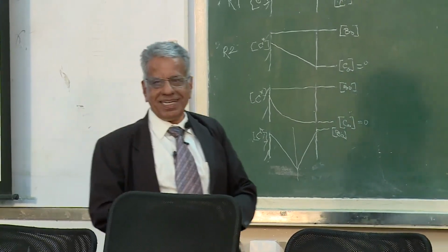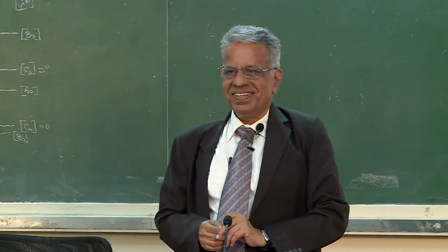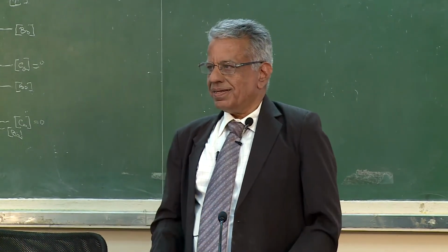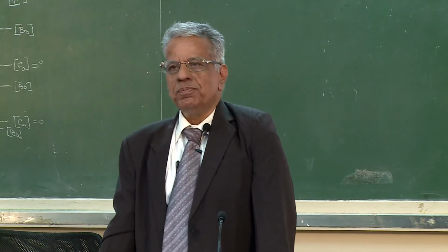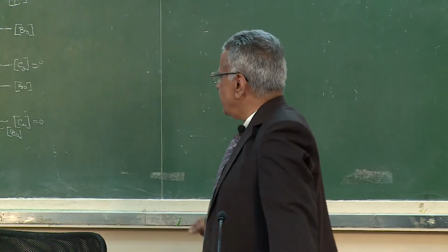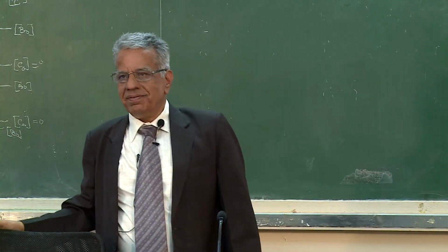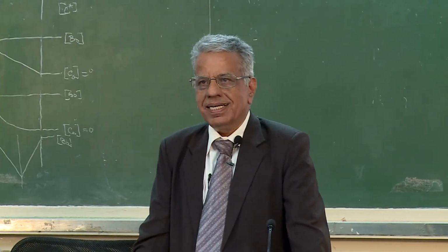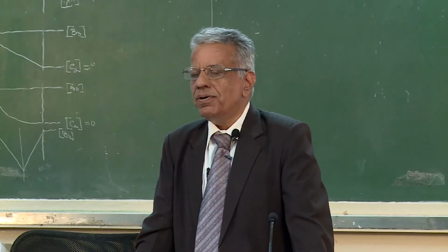After having known that, then what is to be seen? Find out the overall rate, and try to bring it in either regime 1 or regime 3. Either you try to bring it here or bring it here. Find out M and N, find out Kmn, do dissolution at various temperatures, get rate constants. Knowing these 3, and interfacial area and mass transfer coefficient and hold up.